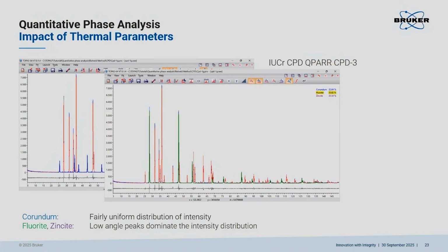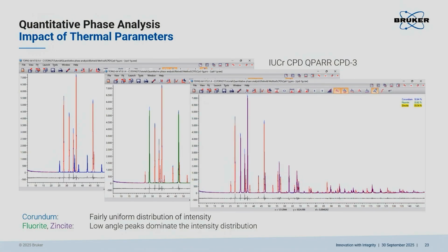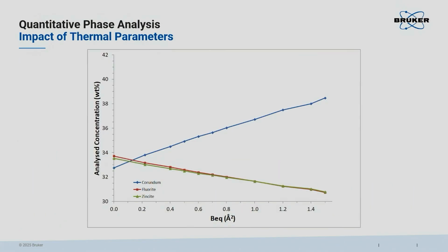So the impact of thermal parameters is a different intensity distribution over 2 theta. And if you have phases where the intensity distribution is different, where you have a lot of high intensities maybe for one phase at low angles 2 theta, and another phase has high intensities more in the high angle region, then you know that you have a potential problem with thermal parameters. The zinc oxide behaves similarly. So what does that mean in practice?